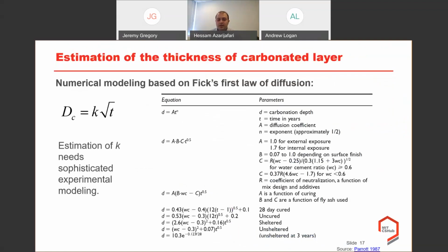Let's go talk about the numerical modeling. All the numerical modeling that I have known so far, or most of them that has been published, is following Fick's first law of diffusion. For Fick's first law of diffusion, as you can see on the equations on the left, the carbonation depth dc is a function of k, which is the coefficient of carbonation, and the square root of time. And all the previously developed and reviewed equations for the carbonation follow the same pattern.